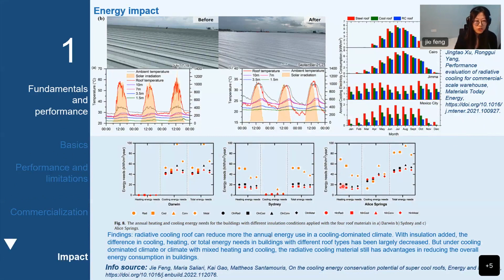In our recent research, we compared the energy saving potential of cool roofs in Australian cities during the year. We found that the radiative cooling roof can reduce more of the annual energy consumption in a cooling dominated climate. If we have insulation, the difference between different roofs can be largely decreased. This is pretty much our research outcome using the energy simulation.